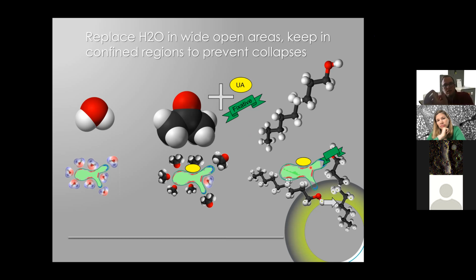You increase the density here locally so that the electrons will not go through too easily, and then you will gain some contrast in your TEM. It's not only the heavy metal salt that gave some contrast. The proteins themselves also have a density, and they will slow down some of the electrons. So basically, depending on your electron microscope setup, you will have some contrast even without contrasting agent, but it will be very mild.